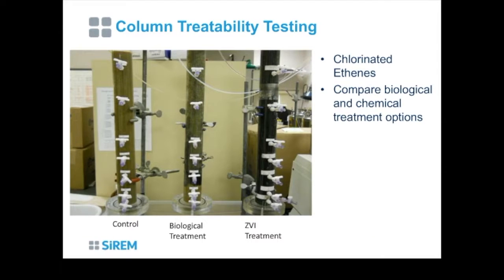Here are some photographs of some actual columns set up in the laboratory. One thing I'd like to point out is the zero-valent iron is actually black, so we've got granular zero-valent iron packed into the column here. We have a control here where we're not adding any amendments at all. In the biological column here, we've been adding electron donor, and what we see is, once the reducing conditions were established, you can see the blackening of the column around this port right here that I'm circling, and that shows where we had establishment of reducing conditions for anaerobic bioremediation.